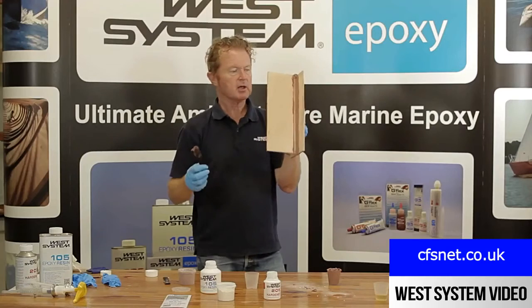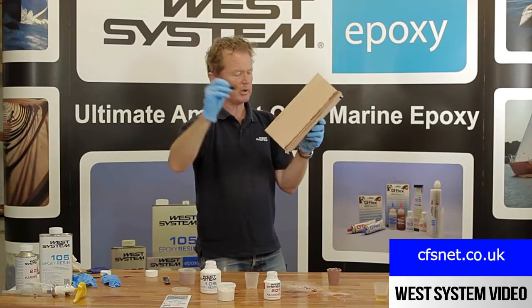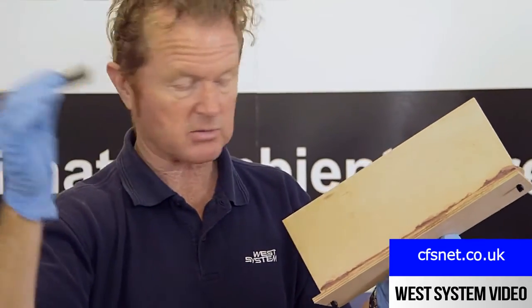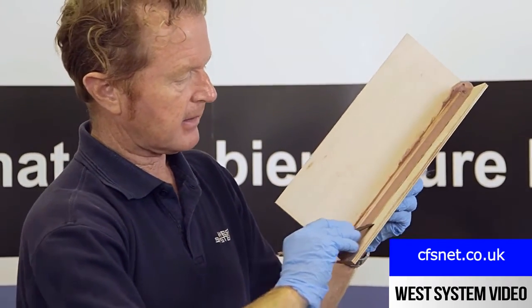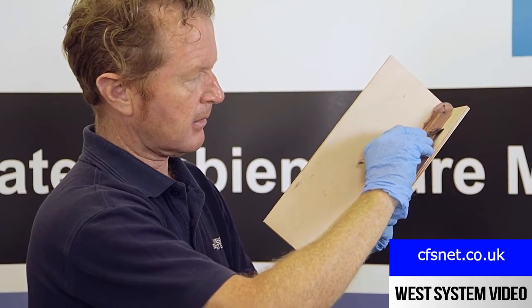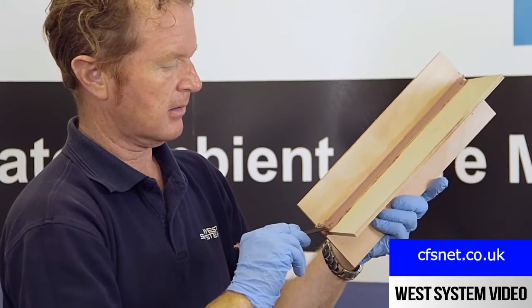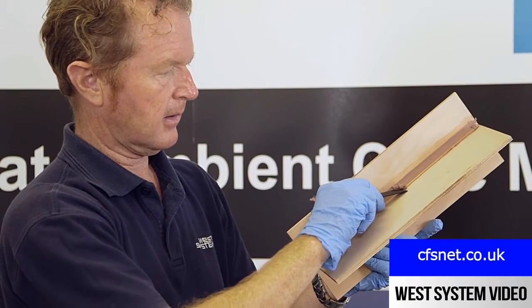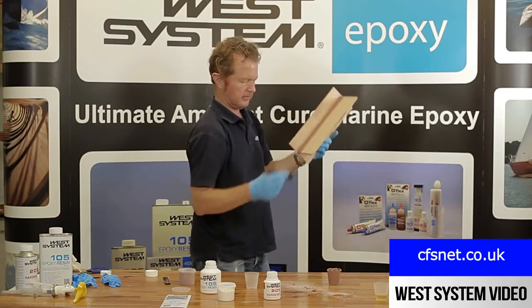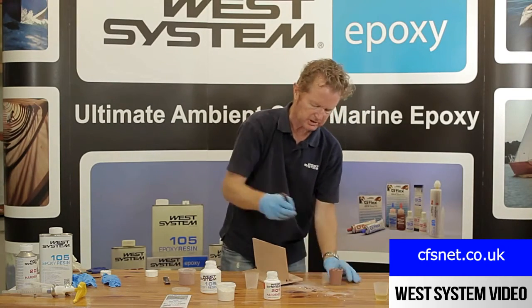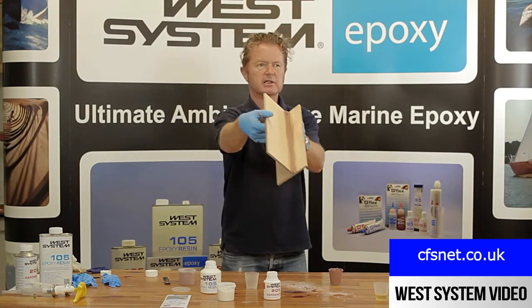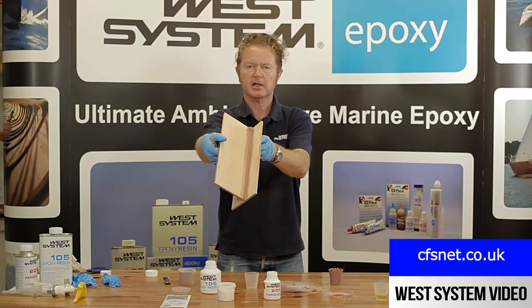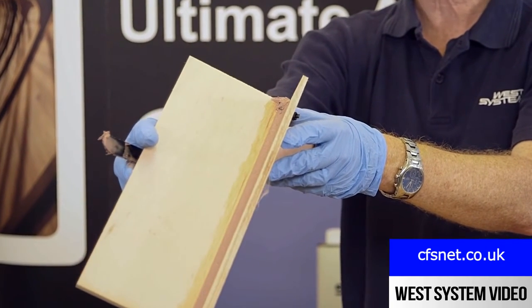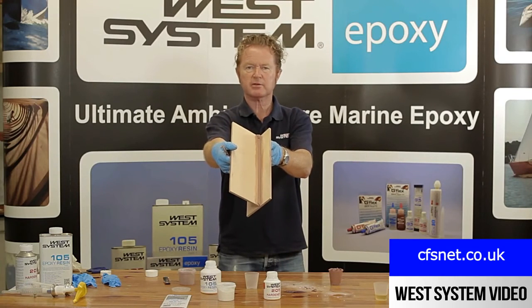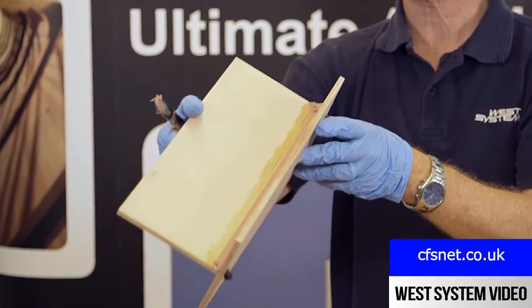fillet. We need to clean that up, and we clean that up with the chisel point on the other end of the plastic mixing stick. I told you that these were very, very neat. Replace the waste, and now we have a very, very neat epoxy fillet, a combination of West System 105, 205 resin and hardener mix, and 407 low density filler. This will make a very, very strong fillet on small plywood dinghies.